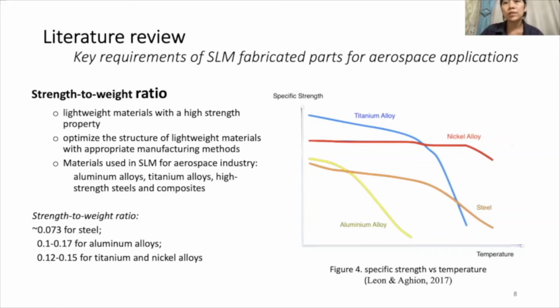Also, materials, especially aluminum alloys, continue to be the dominant materials in the aerospace industry. Composite materials are gaining increasing interest and competing with aluminum alloys in many novel applications in the aerospace industry. Materials with high strength mechanical properties with relatively low weight are known as the best strategy to improve fuel efficiency and get closer to the green production of aerospace components with low CO2 emission. The general commercial materials used in the aerospace industry are aluminum alloys, titanium alloys, high-strength steels, and composites, which typically account for more than 90% of the weight of an airframe.